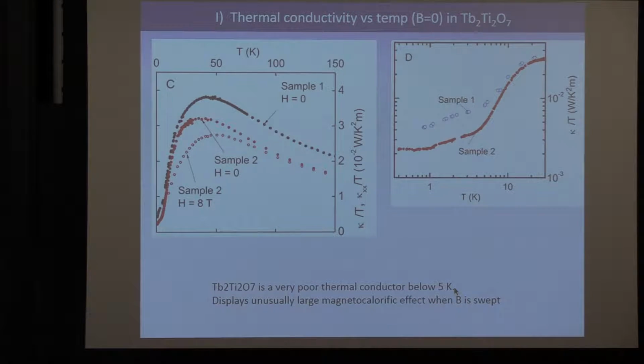So here's the thermal conductivity. When you cool down, I'm dividing by T so that this gets amplified a little bit, right? So I'm removing an extraneous factor of T that appears in all thermal conductivity expressions. So it reaches a peak, and then it comes down and it becomes a very poor thermal conductor below 5 Kelvin. So I'm blowing up the region below 10 Kelvin, and you can see that the phononic decrease gets interrupted, shorted up, so to speak, by an excess that we would like to ascribe to spin excitation.